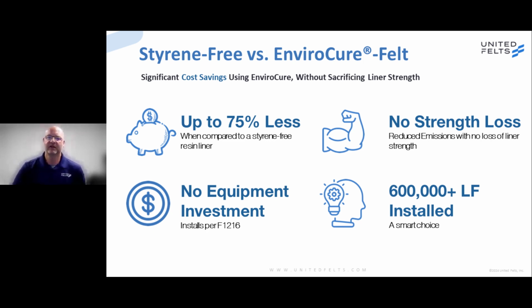So to sum it all up, the cost savings for EnviroCure are quite significant. It's up to 75% less when using the EnviroCure material as compared to a styrene-free resin liner. There's no significant strength loss because we're still using the same resins that most CIPP installers and utility owners are accustomed to. There's no additional equipment investment required by the contractors. They are ready to go with this product with what they're currently using in their CIPP installations. And it's a smart and proven choice. There's 600,000 feet of this material in the ground already.